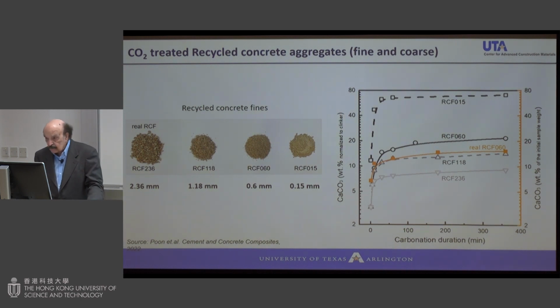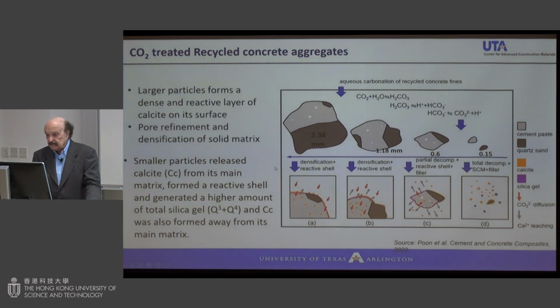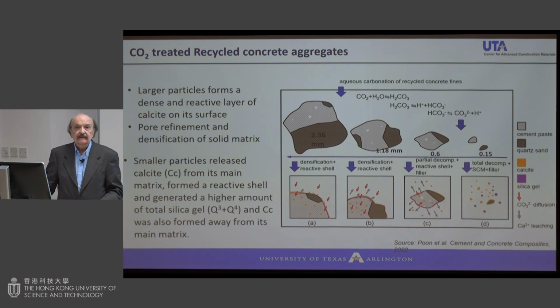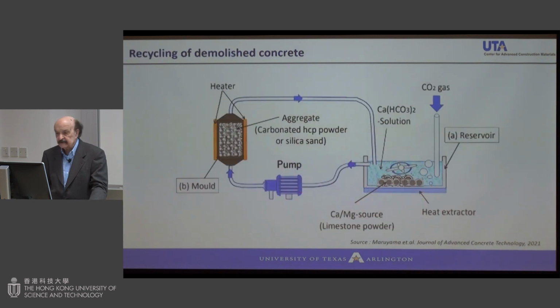But then if you look at the smallest size and carbonated, 0.15 millimeter and smaller, after carbonation you have calcium carbonate and silica gel. And then that acts as a pozzolanic material. So that's quite interesting. With a coarse aggregate, you have carbonation and it forms a nice layer of calcium carbonate. But with very, very fine aggregate, you have calcium carbonate as well as silica gel, which acts as a pozzolanic material. This is some work done in Japan, and a lot of people say you have construction waste.